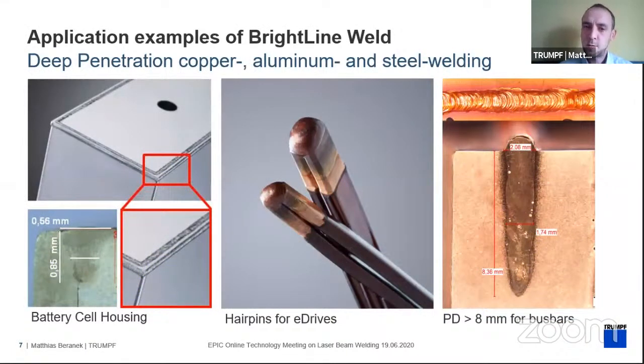In comparison to the green laser, where we have heat conduction modes in welding, Brightline, especially in combination with copper, is meant for deep penetration, higher penetrations. On the right side, maybe one of the most extreme examples is the penetration of over 8 millimeters into copper. And this is what we can realize here with the multi-spot Brightline Weld technology. These are 2 things, mainly in the copper area, that we are working with at the moment. There is a ton of applications coming up from that. And there's a bright future for all of the laser technology, actually.